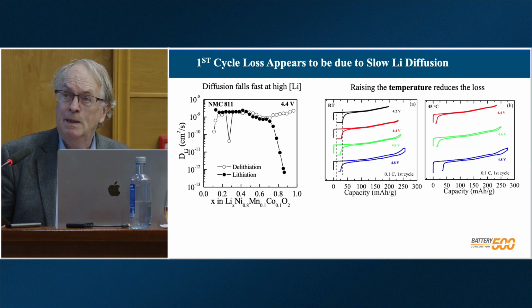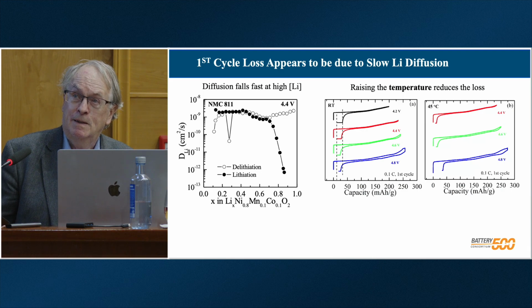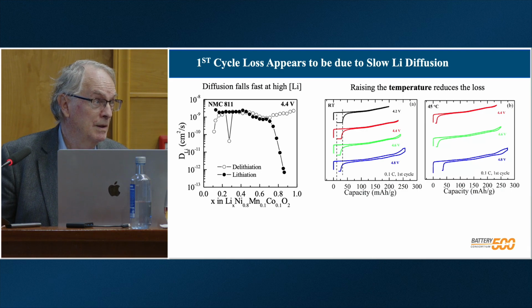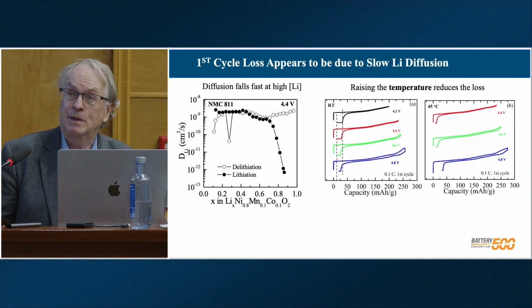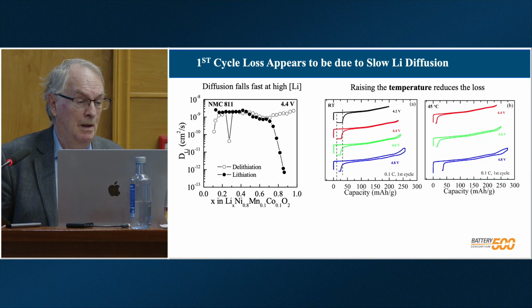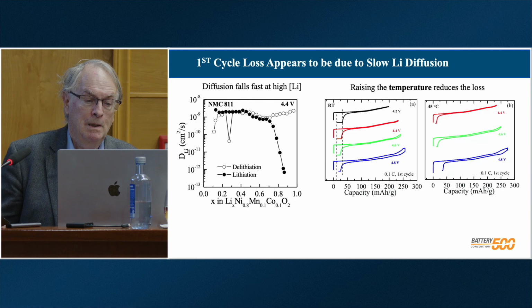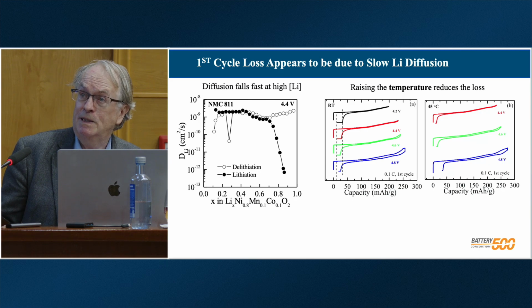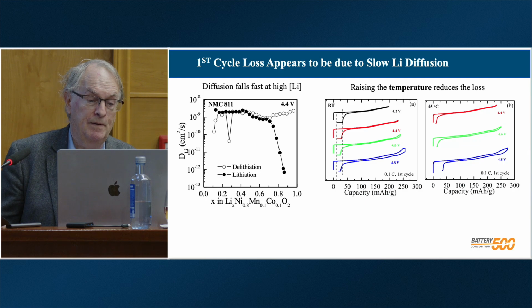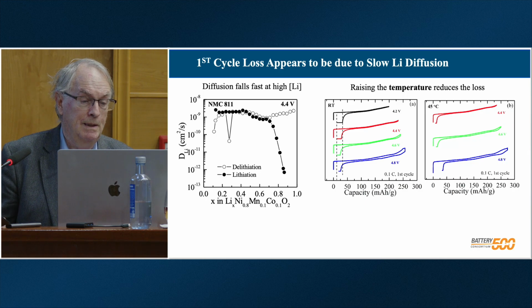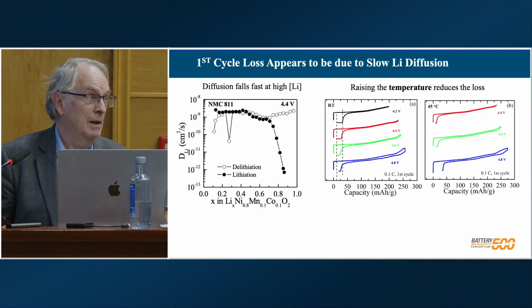So I show you in the center plot there, the effect of going to higher and higher charging voltage. We can get more lithium out, but you can see we still have this issue with the first cycle loss. And you'll see that flat part at the bottom there, we discharge at 2.8 volts, then we hold it there for 4 hours. So you can see we're getting some of the lithium back in. On the right-hand side, we've raised the temperature from room temperature to 45 degrees centigrade, and you can see that first cycle loss has been drastically reduced, which says this is a kinetic phenomenon.